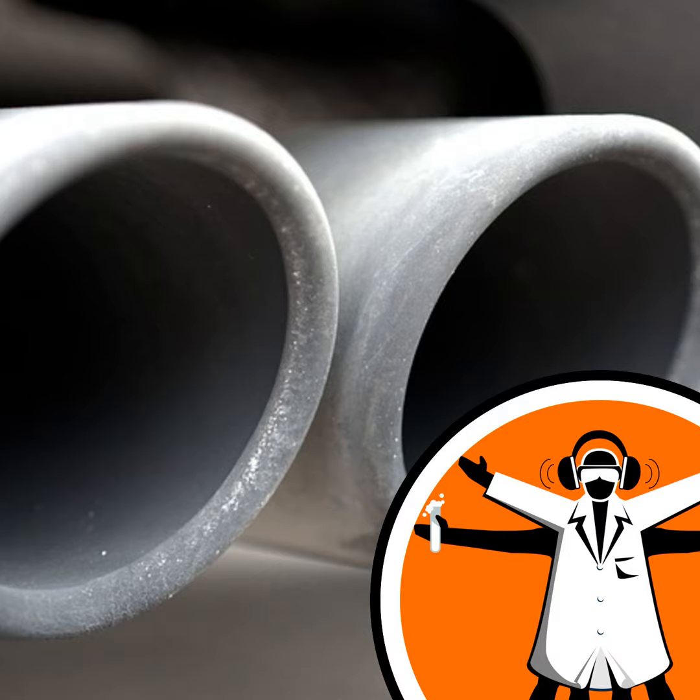What they think is happening is the carbon monoxide comes down, binds to a platinum nanoparticle, then the oxygen atom that reacts with the carbon monoxide comes from the cerium oxide, not from oxygen molecules in the air. So you'd usually expect it to come from the oxygen in the air, but it's that support that's then providing this oxygen instead. Yes, so the support is providing the oxygen atoms that react with the CO, and then it's only later on that the support is regenerated from oxygen molecules in the air reacting with the cerium oxide. So their trick was they found they were able to get the cerium oxide in a nice state, allowing oxygen atoms to transfer from the solid support onto the CO molecule to make it into carbon dioxide.